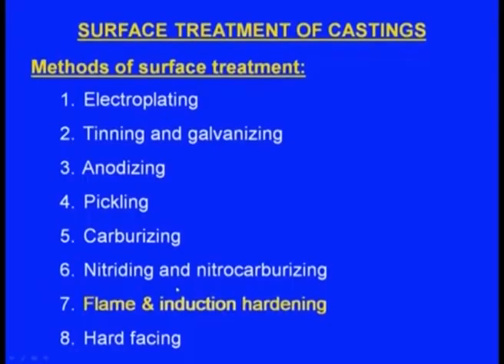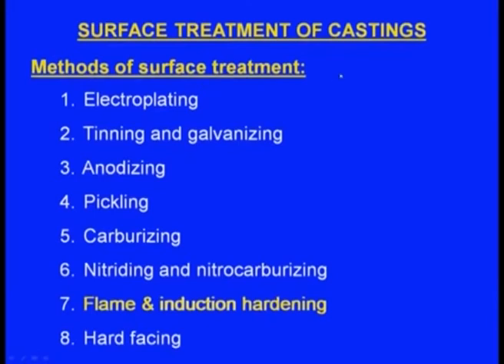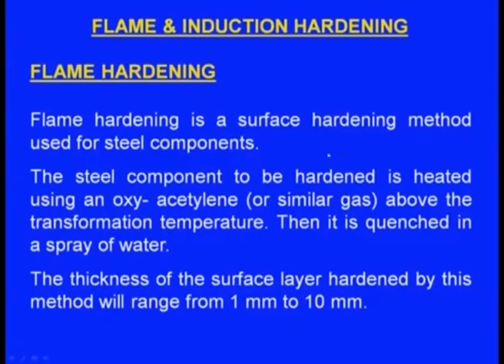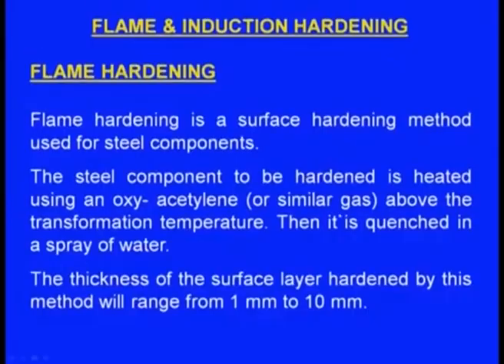Next one is flame and induction hardening. This is the next method in the surface treatment process. Flame hardening is a surface hardening method used for steel components. The steel component to be hardened is heated using oxyacetylene gas above the transformation temperature. Then it will be quenched in a spray of water. The thickness of the surface layer hardened by this method will range from 1 mm to 10 mm.